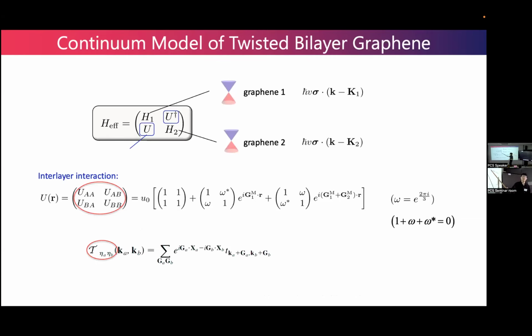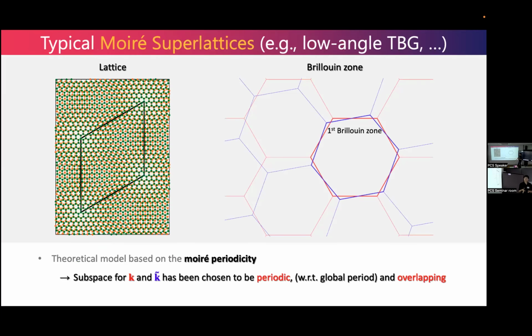So the Hamiltonian looks like this. The diagonal components are just the intralayer component, and the off-diagonal component shows the Umklapp scattering. However, in a typical conventional moiré superlattice, we choose the subspace of K and K tilde to be periodic with the global periodicity because the theory depends on the moiré period.